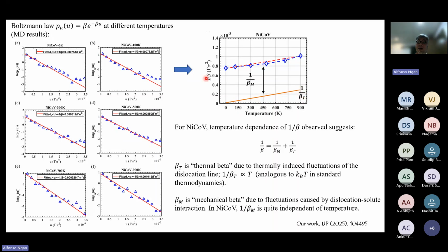So in this case, with this observation, we can argue that the mean energy comprises an athermal part, which doesn't depend on temperature, as well as a thermal part in the usual thermodynamic sense. The athermal part is obviously due to the strong locking, mechanical locking or pinning of the dislocation from these vanadium sites. And that's why this is rather athermal.